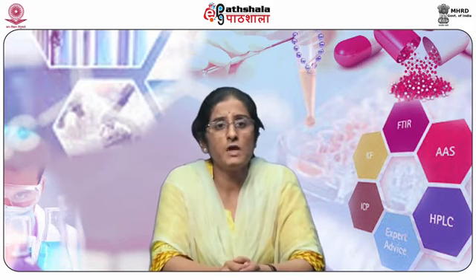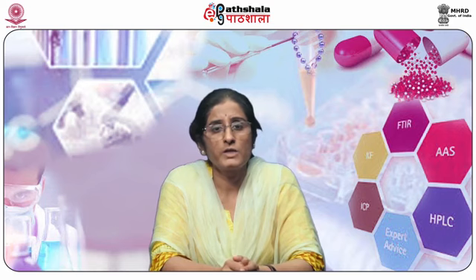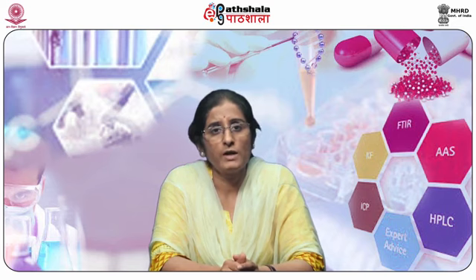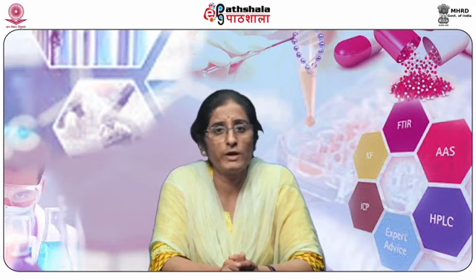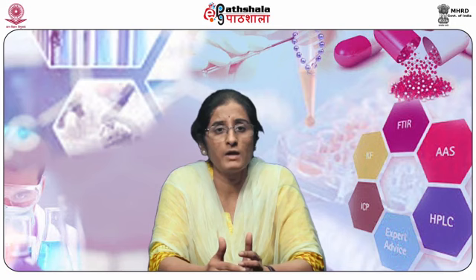The first one is the powder glass test. It is generally carried out on crushed grains of a specific size. It measures the amount of alkalinity leached from the glass under controlled conditions of elevated temperature by using purified water. Second is the water attack test. It is generally conducted on the whole container and is used only with type 2 glass.